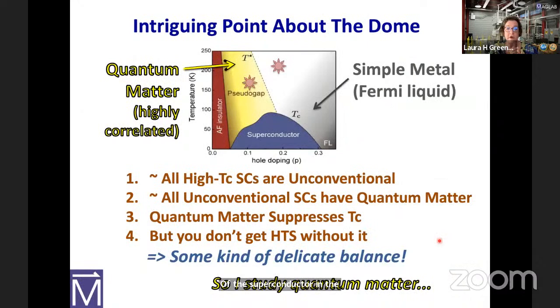As I told you, I study what's over the dome. One of the reasons is an intriguing point about the dome: on the far right side, where you have a Fermi liquid, TC goes down. On the left side, we have highly correlated electrons in a high temperature cuprate. It's called a Mott insulator. If you do the calculation, this should be a great conductor, but it insulates due to the electron-electron correlations. And then on the left side, TC also goes down. So too little or too much correlation is bad for superconductivity, but you don't get high TC without the correlations.